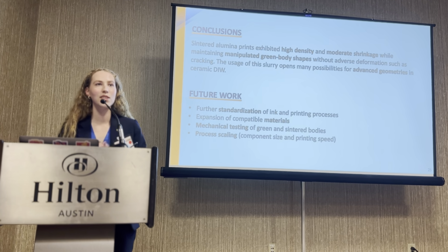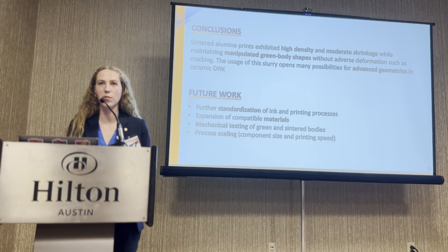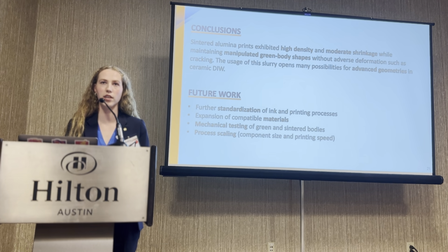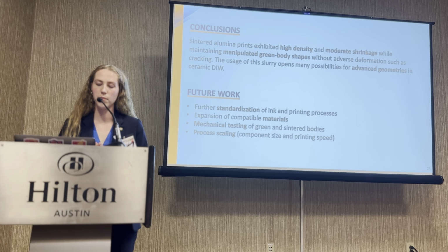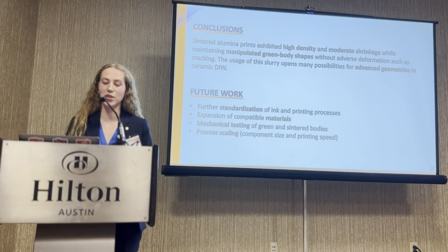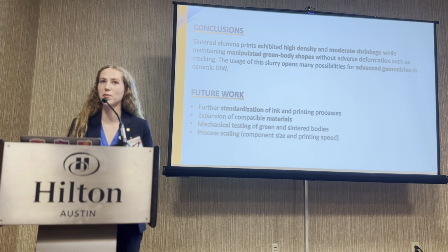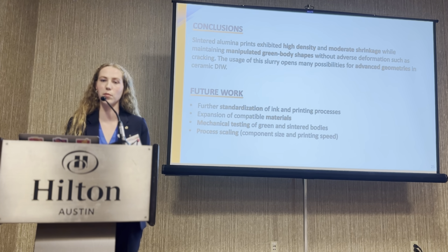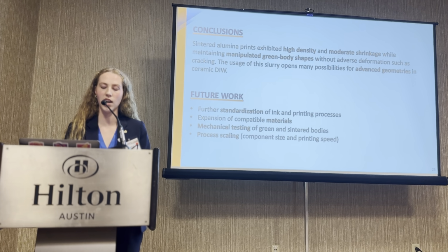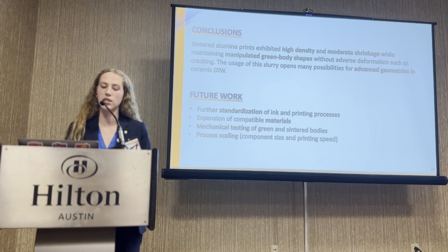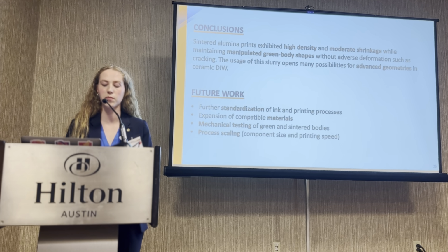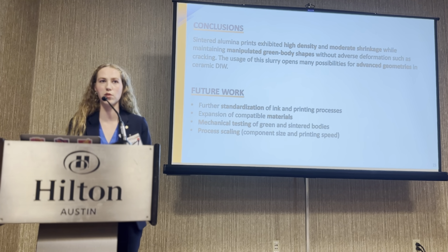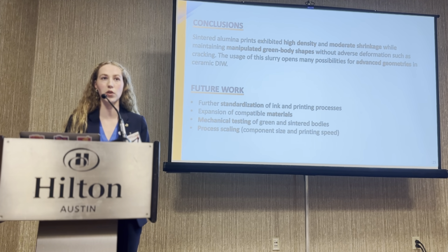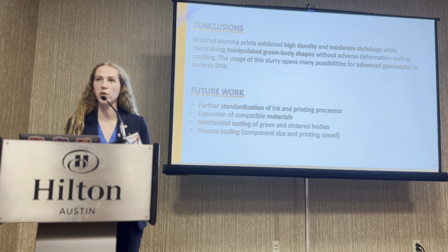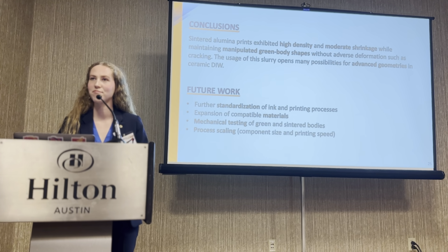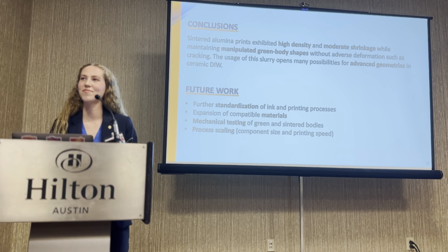So in conclusion, our sintered alumina prints exhibited high density and moderate shrinkage without any issues such as cracking experienced by previous literature, and it maintained those manipulated green body shapes, which opens lots of potential for more advanced geometries in the field of ceramic robocasting. In the future, we're looking at further standardizing those ink and printing processes, expanding the compatible materials, testing those green bodies and the sintered bodies for mechanical properties, and finally, looking at process scaling for larger components and faster printing of components.